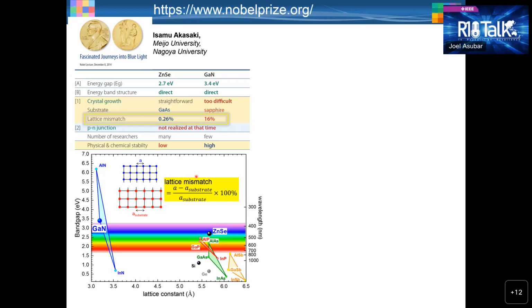Lattice mismatch is a measure of how much difference there is between the lattice parameter of epitaxial layers and the substrate. To enable epitaxial growth, lattice mismatch should be as low as possible. The lattice mismatch for high quality epitaxial growth should be less than 1%. Again, the lattice mismatch between gallium nitride and sapphire is about 16%. In contrast, the lattice mismatch between zinc selenide and gallium arsenide is just 0.26%. Therefore, zinc selenide attracted more researchers during that time.